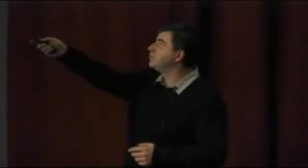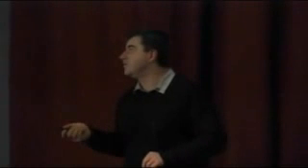And then if we have two layers of graphene stuck between boron nitride, which is an insulator, you can study transport not only in plane but also out of plane, for example tunneling between those two layers, and surprisingly, even a single layer of boron nitride acts as a good insulator. It shows some exponential behavior, and if you take a few layers, the behavior becomes different. It's clear exponential behavior for, say, 4 to 6 layers of boron nitride.